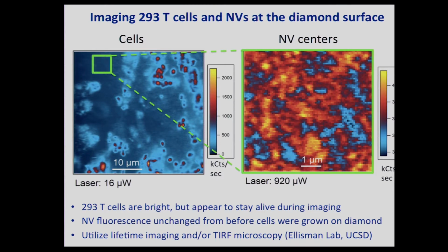But these are cells grown on the diamond. If we look at an area where there's very little autofluorescence, potentially no cells there, we take a confocal image, and this is a confocal image showing NV centers, which is almost identical to the image that we took before plating with cells. So the nice thing is that the NV fluorescence is unchanged from before the cells were grown on the diamond. The other nice thing is that the 293T cells, although they're bright, appear to stay alive during imaging. We confirmed this by putting some stains in afterwards to make sure they were alive.